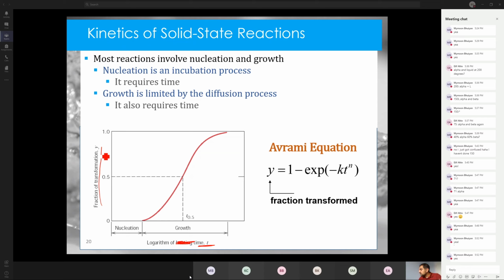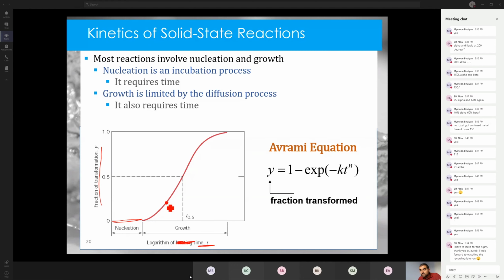And what you find is there is an incubation time, there is a delay. It doesn't start freezing immediately. Some time will pass. If you open the freezer and took it out after 5 minutes, you'll find it's still completely liquid. You put it back in, and maybe after 30 minutes, you find it's beginning to freeze. It's slushy now. Some water, some liquid. So pretend you had an easy way of measuring the amounts. You can put it on your diagram. So after 20 minutes, I found 20% solid. After 70 minutes, it was 50% solid, and after 2 hours, it was 100% solid.